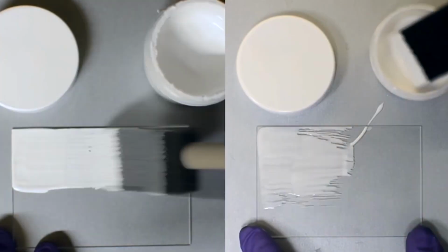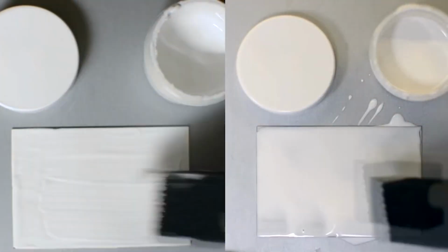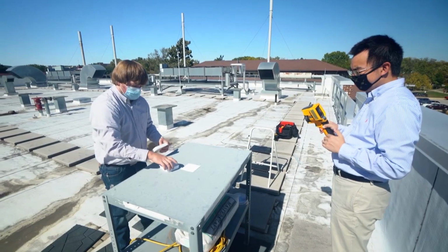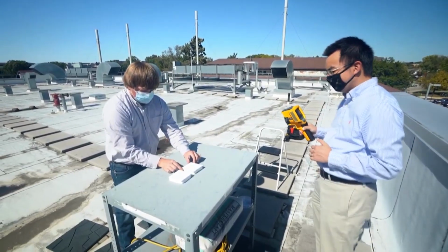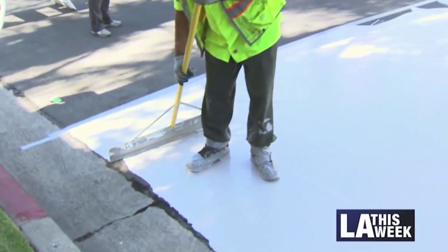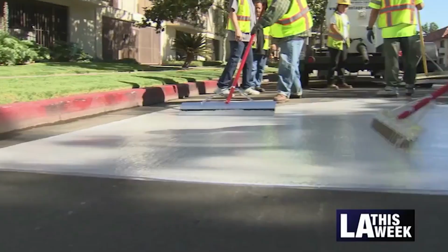However, Purdue Ultra White also has its drawbacks. For the coating to function properly, it needs to be applied in a relatively thick layer, up to 0.5 millimeter thick, which is quite a lot by the standards of modern paint coatings. In addition, this paint is relatively heavy. To achieve the necessary thermoradiative effect, about 700 grams of Purdue Ultra White must be applied per square meter of surface. And the strength of the thermoradiative effect itself is not especially impressive for such parameters.